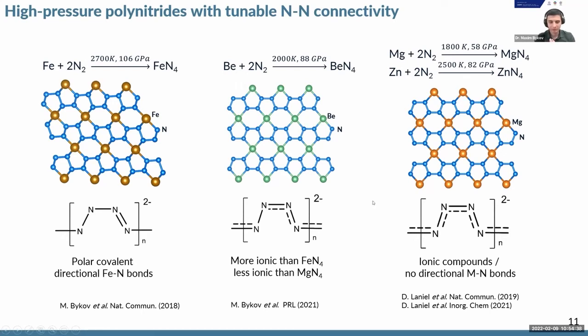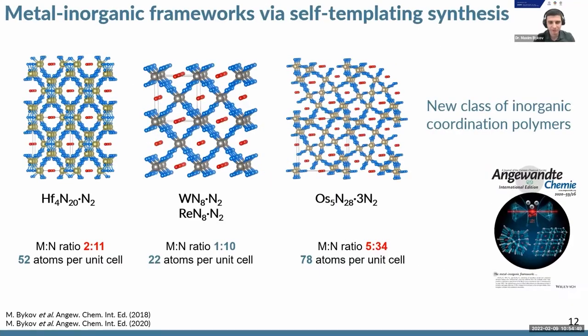So although all these 4 compounds are quite simple and they probably could be modeled in advance, sometimes high pressure chemistry in diamond anvil cells results in really complex compounds. For example, a series of metal-inorganic frameworks, which we synthesized with the transition metals hafnium, tungsten, rhenium, and osmium, show that such frameworks form above 1 megabar, where we have channels in the structures, and these channels are filled with dinitrogen molecules.